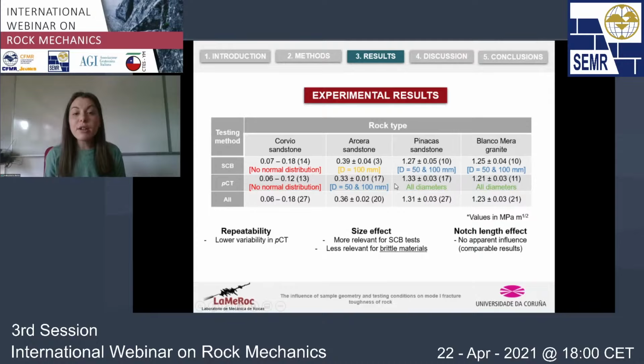But in the other cases, what we can see is that there was a lower variability in the PCT, as we observed from the graphs. We can see it here, for instance, in the case of the Arrera sandstone, the value of the standard error of the mean is lower for the PCT than for the SCB.